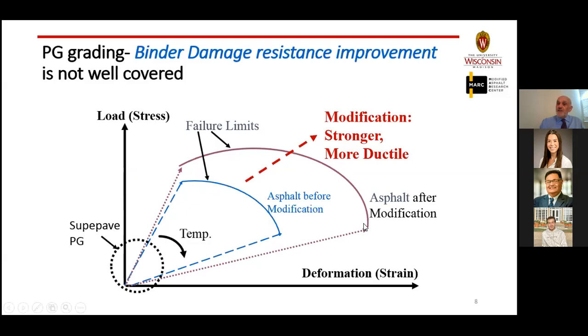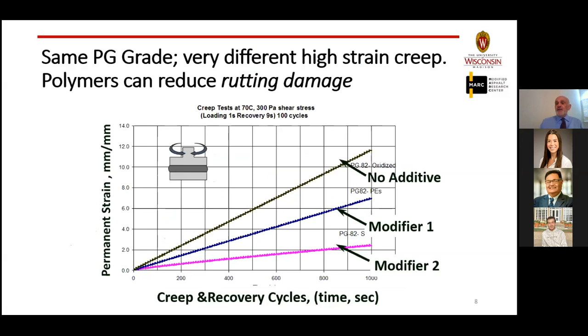Well, again, if you look at this chart, you will recognize that what's important is this region. The most important difference between modified asphalt and unmodified asphalt is this shift in the failure envelope. Whether the failure is in terms of permanent deformation or in terms of resistance to cracking, you see this pushing of the envelope so that the material can take more of these stresses and strains. So I told you, if you go to larger stresses and strains, you will find a much better distinction between these materials. And this is the proof of it.